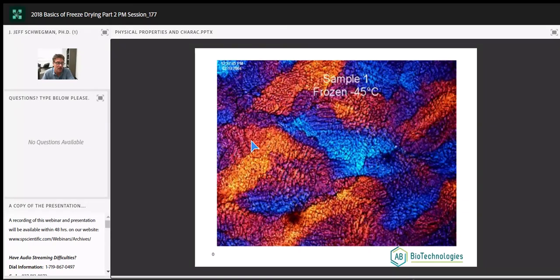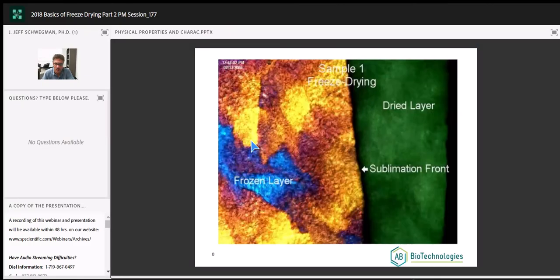So we collect an image in the frozen state, we then kick on the vacuum and start primary drying. In this case, it's minus 45 degrees C, so we're getting an intact dried layer. If we were not getting an intact dried layer, we'd see pores start to open up, or we'd see magenta coming through. And again, magenta is the color of our filter, so we'd start to see light coming through that was magenta. Here's the frozen layer, the dried layer. Here's our sublimation front. That's where we have sublimation going on.